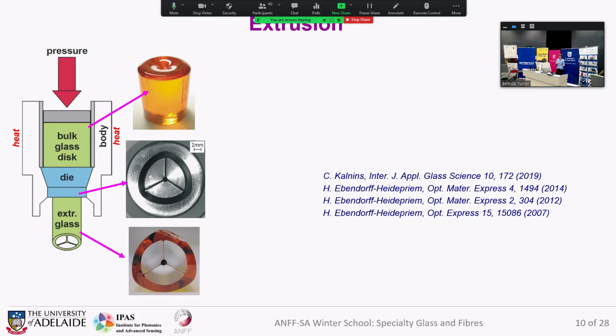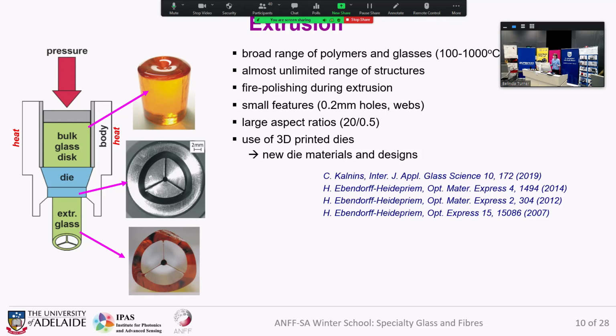So the die exit is the negative of the preform, and via squeezing the glass through the die, we create then air holes all along the preform. This technique is perfectly suited for glasses or materials with low softening point, therefore polymers and glasses with softening points below 1000 degrees Celsius.